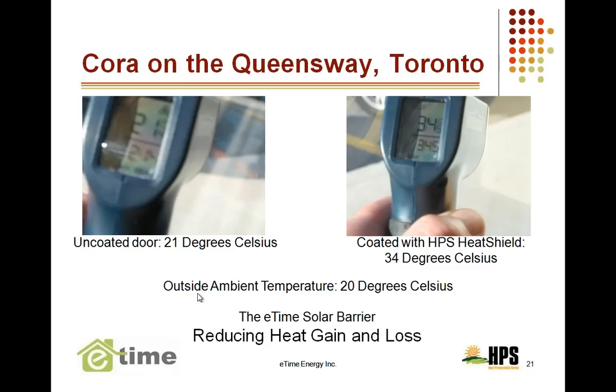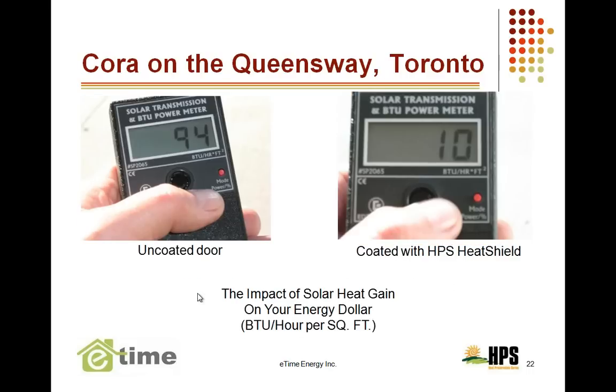The temperature on the heat shield window is 34 degrees, and these were taken about 30 seconds apart in different parts of the restaurant. So the 34 degrees was taken at the front windows. This is the difference. The outside ambient temperature was 20 degrees, and we were able to save the money that was typically lost by the penetration of the heat load coming in. And again, that was 94 units coming in on the uncoated side versus 10 coming in on the coated side.